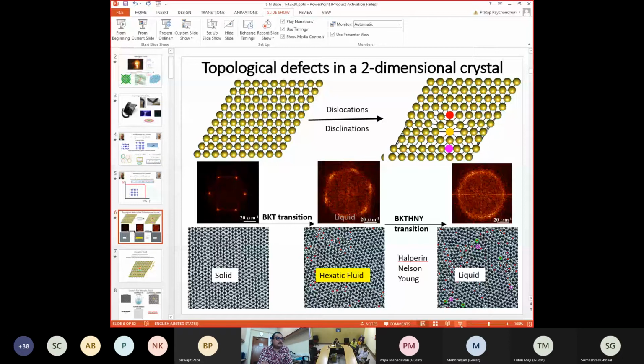So, how would this BKT transition manifest if you translate into a two-dimensional crystal? Suppose I take a two-dimensional hexagonal crystal like this. Here, the topological defect, the equivalent of my kink, which I got in the telephone wire, or the equivalent of the vortex, is this kind of defect, which is called a dislocation, which I have already mentioned to you. Technically, here you can see every lattice point has 6 nearest neighbors. A dislocation is this pair of points where red has 5 nearest neighbors and green has 7 nearest neighbors. Together, this object is called a dislocation.